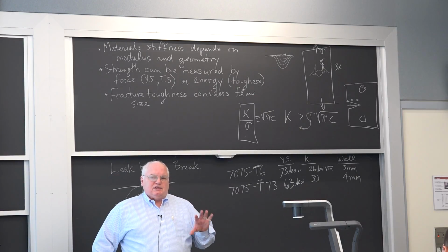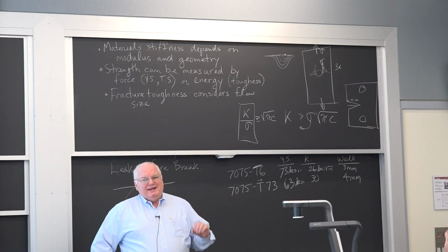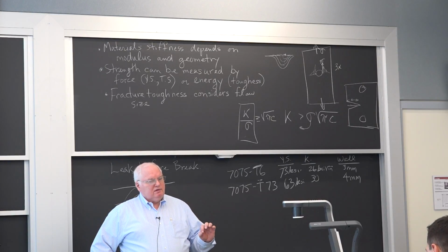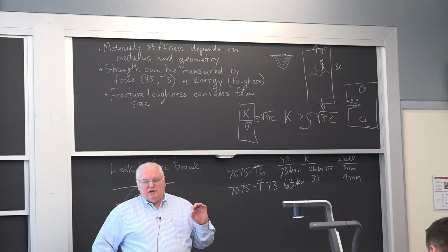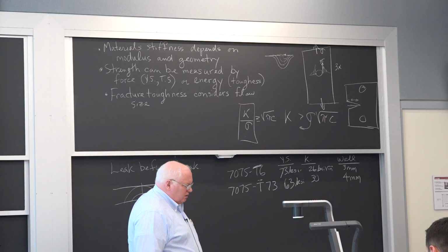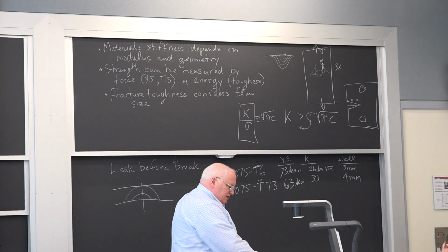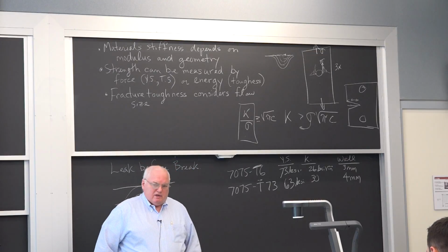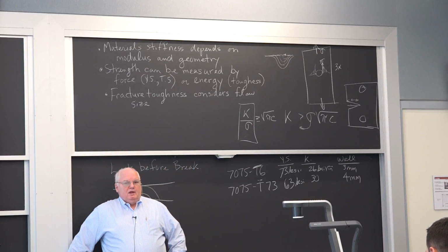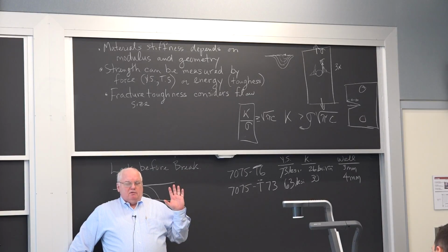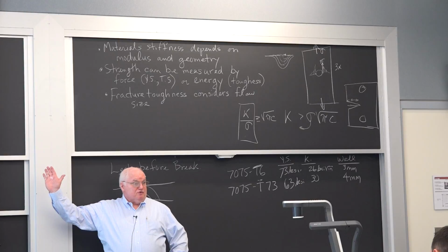So design with structural materials is a balance between strength of fracture by force and strength of fracture by energy. And you need both. And it wasn't until the Liberty ships of World War II that we learned that you had to have toughness as well as strength. You couldn't just go for high strength. We use baseball bats now, okay? Highest strength aluminum. Up there around 100 KSI strength. Off the chart of the ratio analysis diagram that Ashby put together in the 1970s.